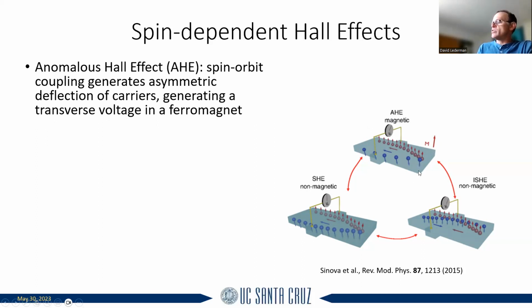In the anomalous Hall effect, what you do is you have a magnetic material, and you run a current, and then you have a Hall voltage that is created like this. Okay, and the reason this occurs, even at zero field, is because you have an imbalance of spins in the conducting ferromagnet, and so you end up with more accumulation. You get asymmetric scattering due to spin orbit coupling, since spin up and spin down electrons scatter differently, but because you have an imbalance of them in a ferromagnet, you end up with a signal like this.